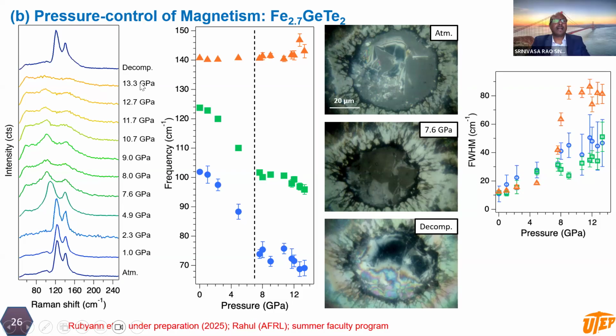And then after the cell is decompressed, we get those Raman signals back. It means that we don't destroy the sample upon applying pressure, and we get the signals back to the normal position after decompressing the cell. So something is going on that is not amorphization of the sample. We are not killing the crystallinity of the material upon applying pressure, but something more is happening to this compound. So we plotted the frequency shifts as a function of pressure, and you see the optical images.